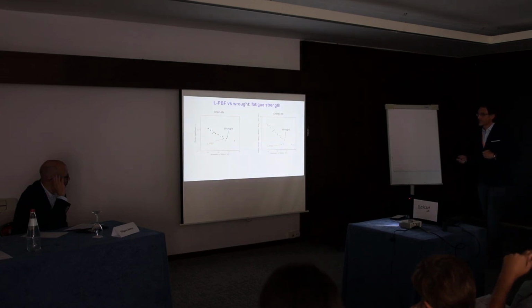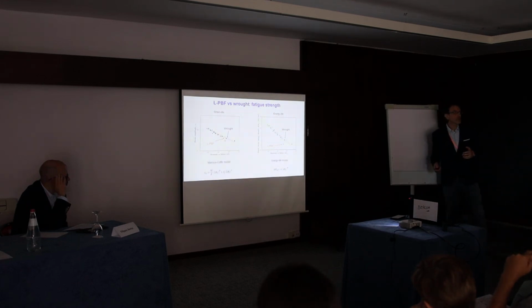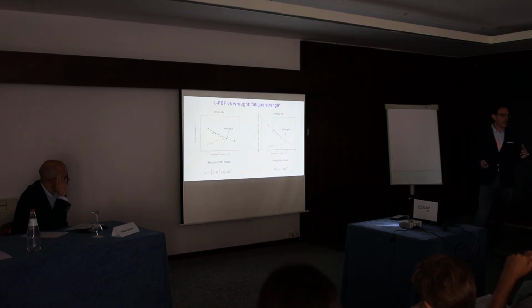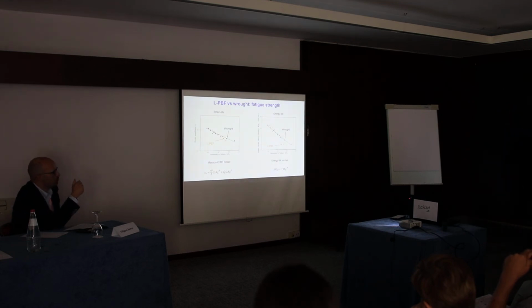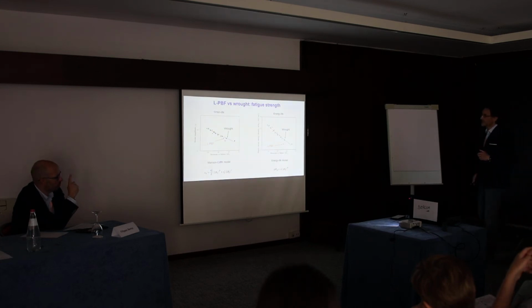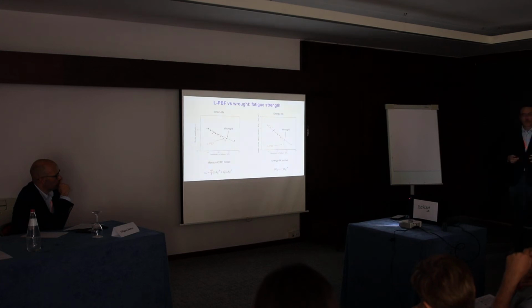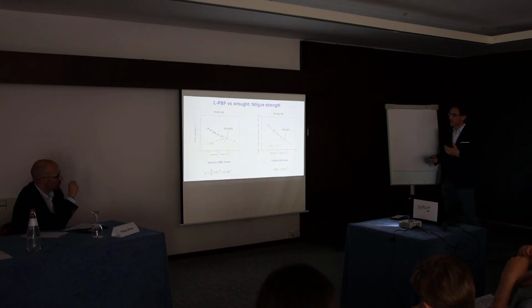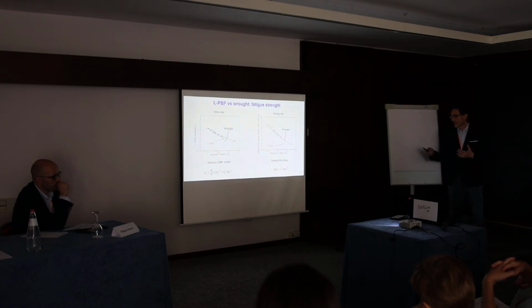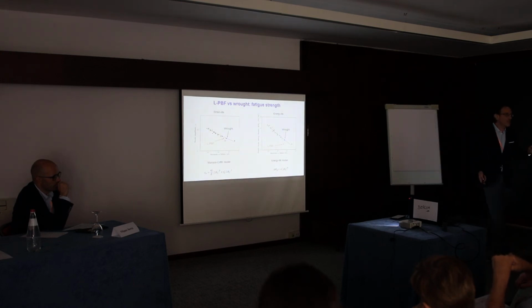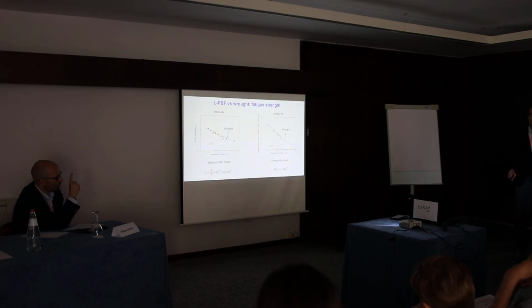But we try to fit the regression lines for both models, Manson-Coffin and energy-based model, and we also perform a statistical test on the slopes of these two fitted regression lines. This is a statistical test based on the Fisher variable, and it revealed that there is a statistically significant difference in the slopes. So we can conclude that also for what concerns the fatigue-like behavior, these two materials indeed have a different, not so pronounced, but a different fatigue-like behavior.